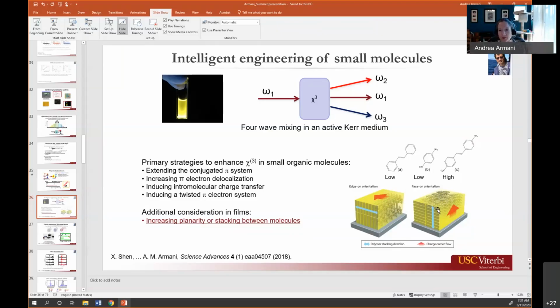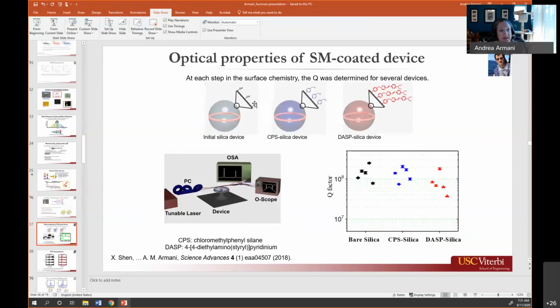And if you think about it, it's the same problem: how do you create an ordered monolayer of a thing on a surface? Using a silane chemistry is a very straightforward approach. In a silane chemistry, you basically take this hydroxyl group, this OH group, and oxygen can be very reactive. Then you use a silane group, and you can buy silane groups from a lot of different vendors, and the silane will bond directly to the hydroxyl group and create an oriented group. So the chlorine won't bond to the oxygen, but the silane will.